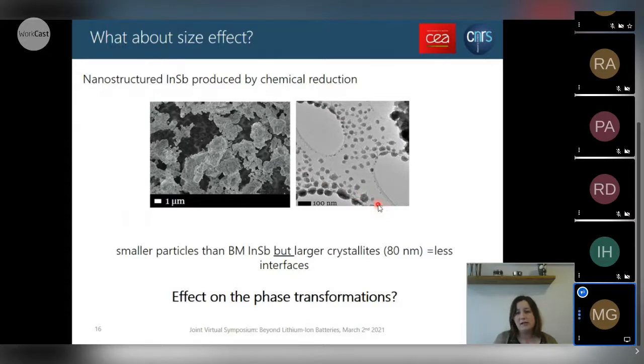But at the same time, these individual particles present a larger crystallite size, on the order of 80 nanometers, which we can infer will create fewer interfaces in the material. So now, what is the effect of this change in morphology on the phase transformation?